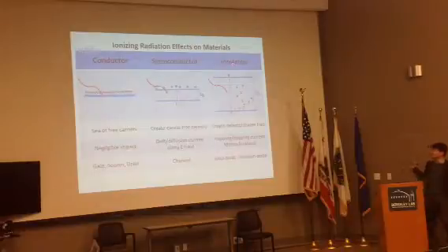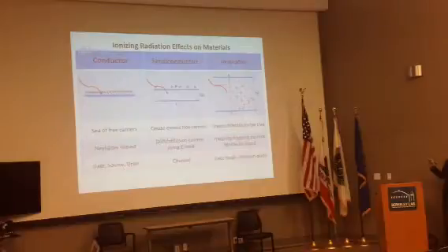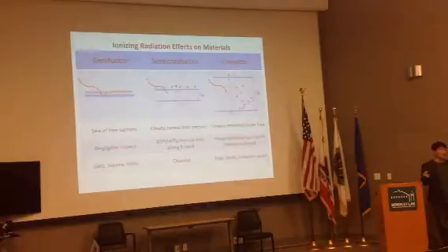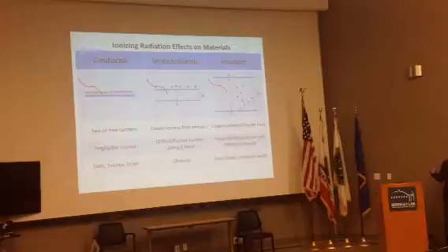And there's an insulator. This graph stands for the band gap of the material. In an insulator, as the band gap is quite large, once this radiation interaction creates electron-hole pairs, the electrons are a very light material, so they are quickly swept away. So it doesn't really matter for the generation of the electrons, but the holes are heavier, and they are bound inside of the lattice.